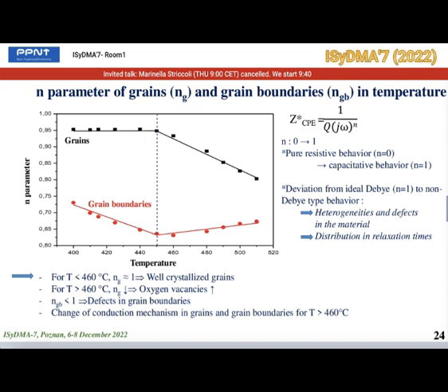And for grain boundaries, the n parameter is far from 1, showing the presence of defects in grain boundaries. We also found on the evolution of the n parameters a discontinuity around 460 degrees, showing a change of conduction mechanism in grains and grain boundaries for T higher than 460 degrees Celsius.